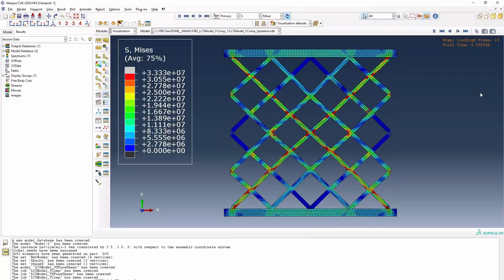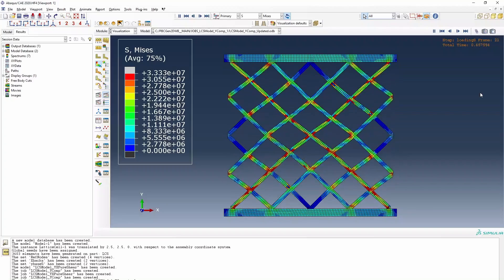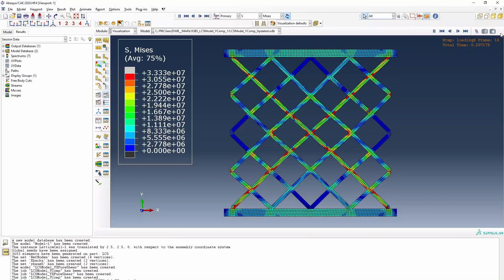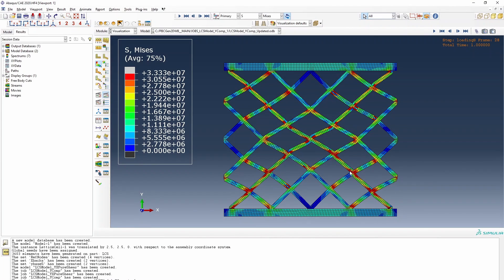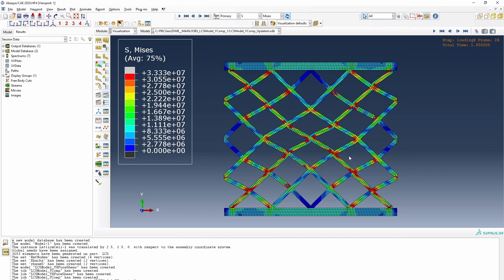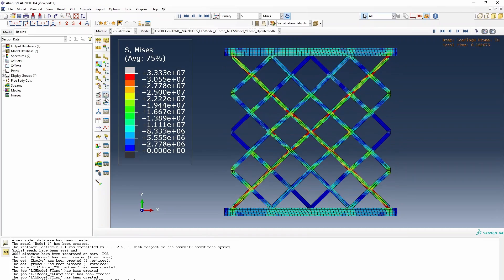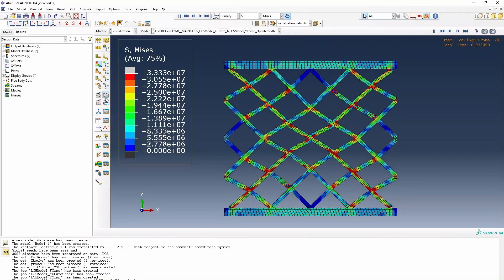Now I move to visualizing results in Abaqus. In the compressive case, the domain compresses under the applied load and stress histories are visible. We can see a buckling effect across the domain, yielding effects, and relatively low loading on the aluminum backing sheets. As the system deforms and builds up plastic load, there is load absorption due to this lattice design. With periodic boundary conditions applied, we're recreating realistic results with good symmetry throughout.